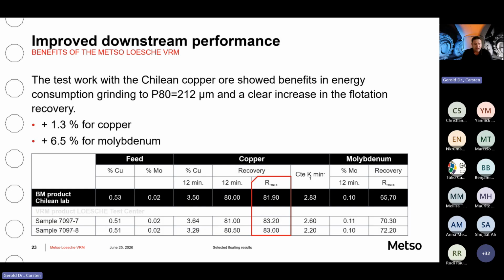And the freshly created dry surfaces respond very well in flotation kinetics. And copper floats very well anyway, but even here we could increase the copper recovery by about 1.3%, and the molybdenum by about 6.5%. And that is explainable.